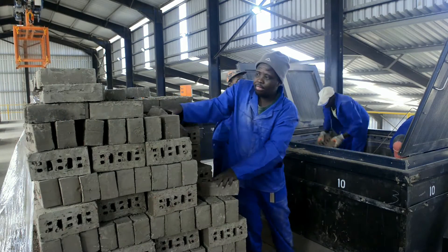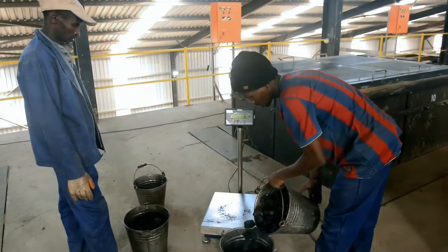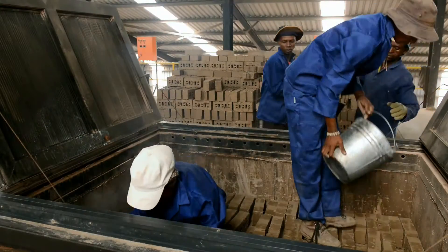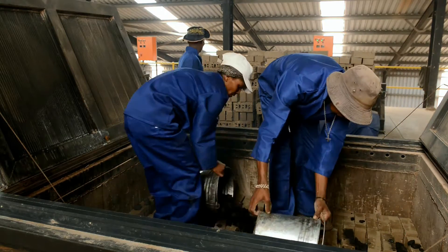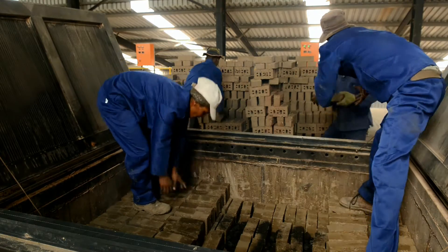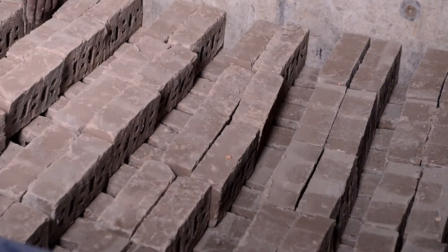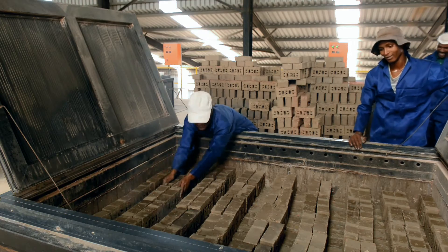Brick packing patterns are employed to allow the controlled flow of air within the kiln. External fuel in the form of small nuts is carefully measured into buckets and then taken to the kiln being loaded. The coal is specifically placed within the batch to enable even firing and will maintain the heat within the kiln. A stock brick batch is made up of four equally spaced opposed layers. Each batch typically has between 456 to 464 bricks. Fourteen of these batches are loaded into the kiln at any one time. Provision is made at the top of each batch to insert the support bars when the batch finally reaches the bottom of the kiln.